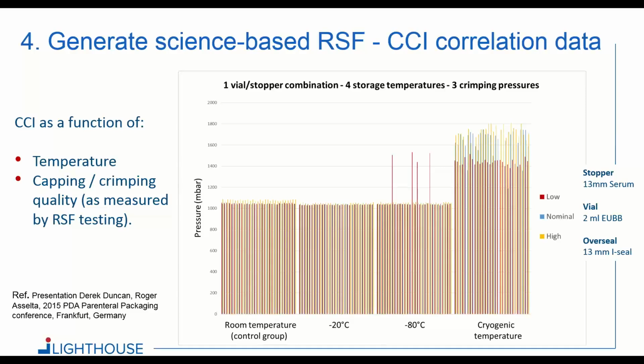And we're also looking at sample sets that were capped and crimped with 3 different pressures. So a low RSF value, or a loosely capped and crimped vial, nominal RSF value, and a high RSF value. And you can see that for this vial stopper combination, you get good sealing at room temperature. You get good sealing at -20 frozen, but you start to see issues at -80. And those issues are happening with the low RSF sample set, so the loosely capped and crimped vial. So again, an indication that the process capping and crimping is important.